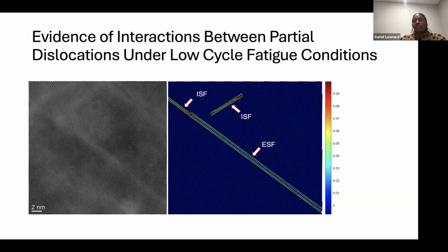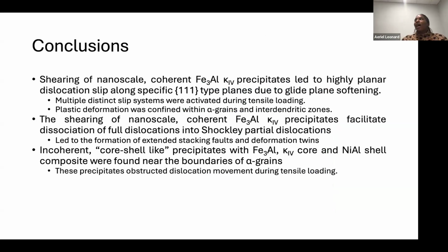And so what the tools that CEMAS has allowed us to do, and the reason why I titled it reviving an old alloy, is not necessarily say, okay, all of the people in the literature are wrong, because when we look at their mechanical properties and our mechanical properties, they're spot on. We actually have very similar mechanical properties, but it's really just not having the tools to truly investigate deformation mechanisms, to really truly understand in the microstructure what is contributing to this increase in hardening or strength that you get when you look at the wire arc condition compared to the coarser microstructure that you get in the cast condition.